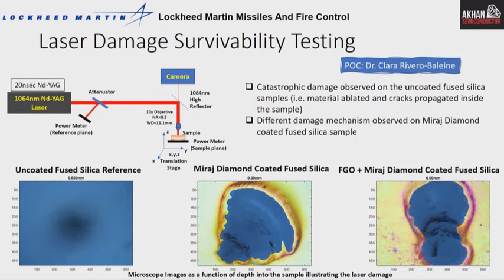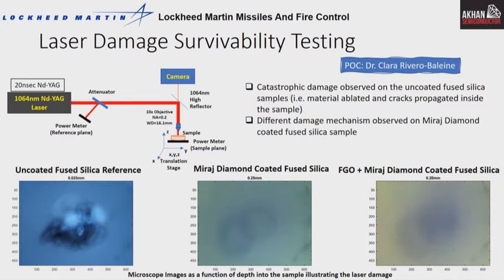This was first attenuated and set to a sample reference point for the uncoated fused silica, and then we were able to ramp under set time and set power to see how the damage was affecting the other samples. As you can see, we'll go layer by layer here and actually show the damage per depth. Something interesting happens. First, in the fused silica sample, we see there's catastrophic failure. Catastrophic failure means that the material is ablated. These cracks continue to propagate through the surface structure, and that's a failure. This means the laser has punched through the system.